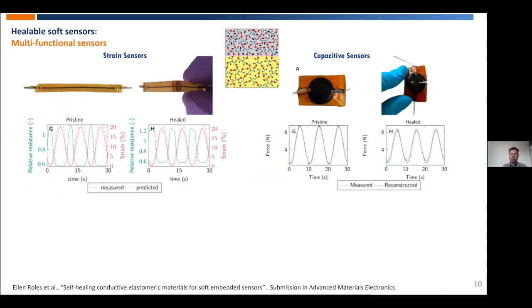Now we've also been developing conductive self-healing materials. So we apply fillers in our material to make them electrically conductive. And then we developed some strain sensors and capacitive sensors, which have a good response. And you can also cut them completely in half, put them back together and apply a heat-cool cycle. And then they recover their mechanical properties, but also their electrical and sensory performance. So this is, of course, interesting because you also increase the lifetime of these components, which are vulnerable as they are composed of flexible materials.